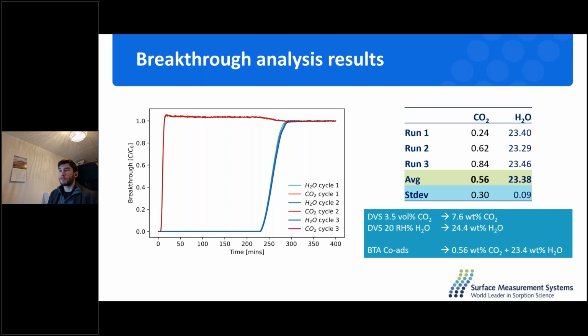But there is something to note here, and this is why I put the standard deviation. The integration of this curve has a bit of error in it because of the noise and the length of time that you have to integrate. There is just a small amount of changes that add up. So the standard deviation is 0.3 weight%. In this case, we're reasonably sure that it is less than 1% CO2, but we still don't have a full picture of how much exactly it is. It is 0.5 plus or minus 0.3 or 0.4, depending on what degree of confidence you want to look at.